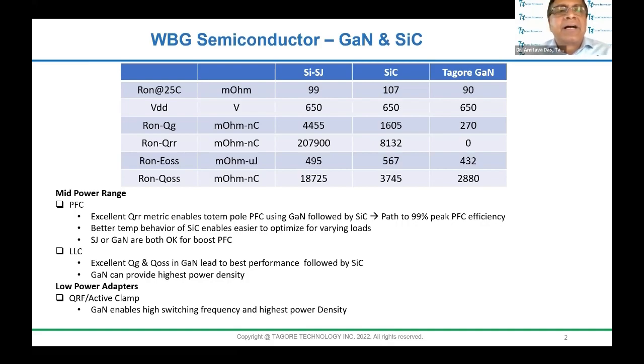So for comparison purposes, I have taken three very similar devices. The superjunction is around 100 milliohm, silicon carbide is around 100 milliohm, and the GaN is 90 milliohm. They're all 650 volt rated. If you look at the first metric, which is Ron times QG, normalized with Ron, you can see that superjunction has a fairly large number, and of course GaN has an extremely good Ron times QG metric, and silicon carbide is actually quite a bit worse than GaN, but much better than silicon superjunction.